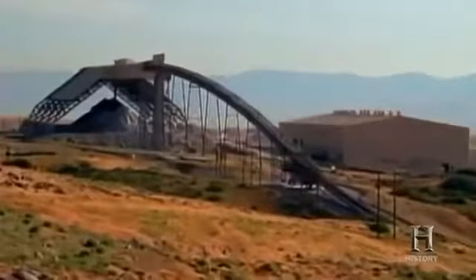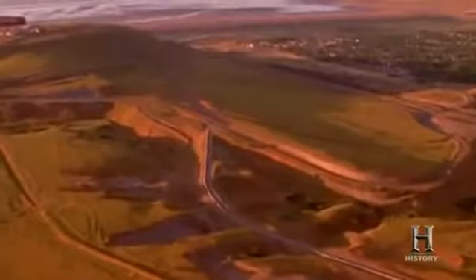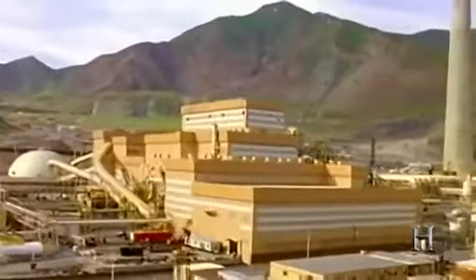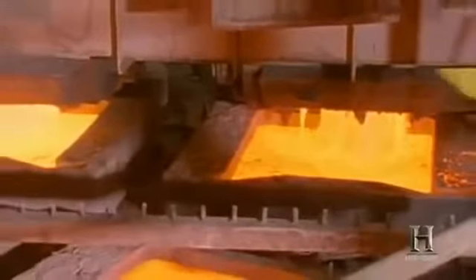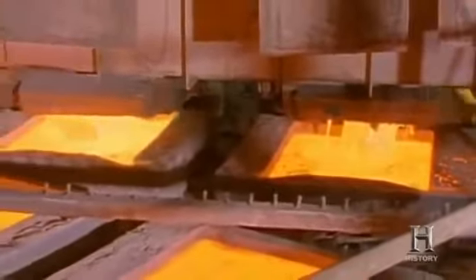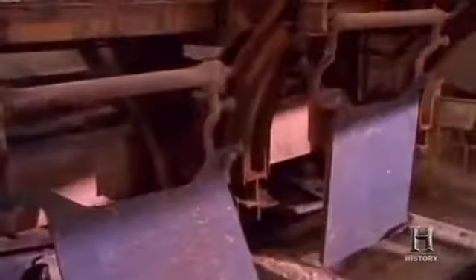After the rock is blasted free and crushed, a series of conveyor belts carries it 5 miles to the concentrator. There, flotation cells separate out a liquid that's 28% copper. The liquid is pumped 17 miles to a smelter, where furnaces refine it to 99.6% purity and it's cast into 700-pound plates called anodes.